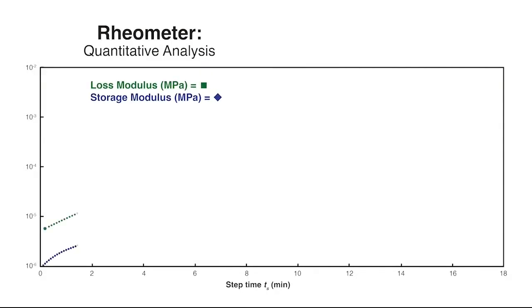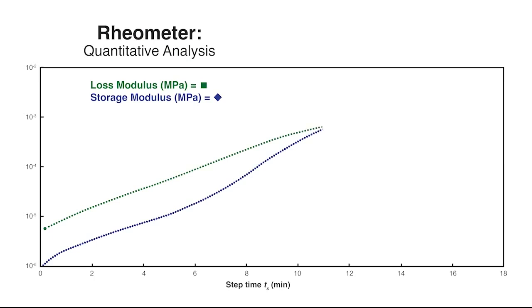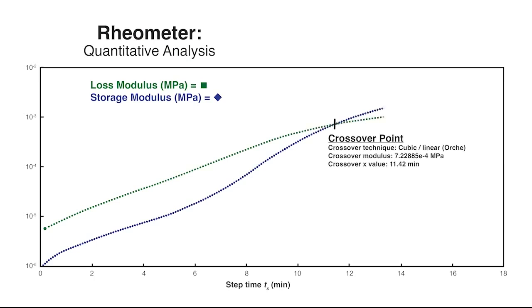In this graph, you will see the quantitative analysis of the loss and storage modulus of a curing thermoset. As the two-component thermoset begins to react, you can see that both the loss and storage modulus increase. They will both continue to increase until they reach what we call the crossover point. At this point, the elastic properties overtake the fluid properties. We relate this to the no-flow point in the reaction, which is analogous to the gel time. Additionally, the rheometer can precisely measure this crossover point at any temperature between -40°C and 100°C. This type of analysis gives your process engineer vital data for manufacturing improvements and optimization.